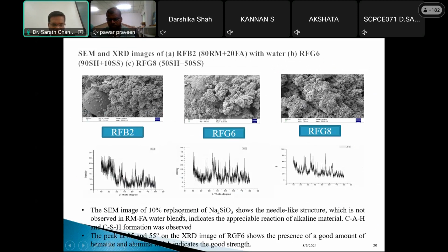The image of 10% replacement of Na2SiO3 shows the needle-like structure, which is not observed in red mud fly ash water blends. You can observe needle-like structures in the SEM image of 10% replacement, which indicates appreciable reaction of alkaline material, and it also indicates that CAH and CSH formation was observed. The peaks at 35 and 55 degrees on the XRD image of the RFG6 combination show the presence of alkaline, hematite and aluminum, which indicates good strength.